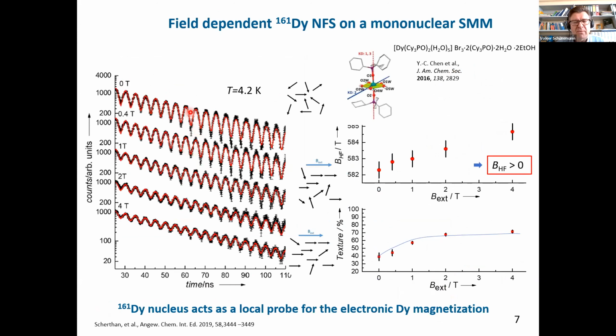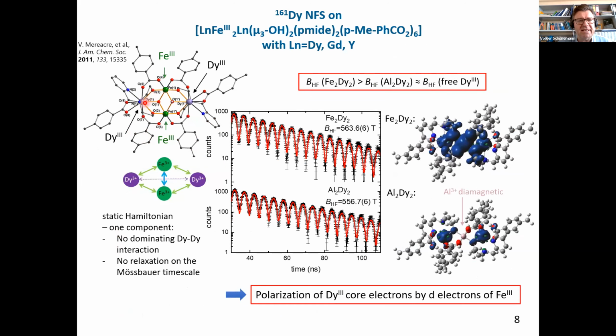And we were interested whether we could apply that as a microprobe, or nuclear probe, for magnetization. So these here are measurements of the same complex in field at 4.2 K, and the hyperfine field could be deduced to be positive, and the texture coefficient here is roughly following the magnetization of the sample. So we have basically the situation where we can use the dysprosium nucleus as a local probe for the electronic dysprosium magnetization. And here's another complex made by the power group.